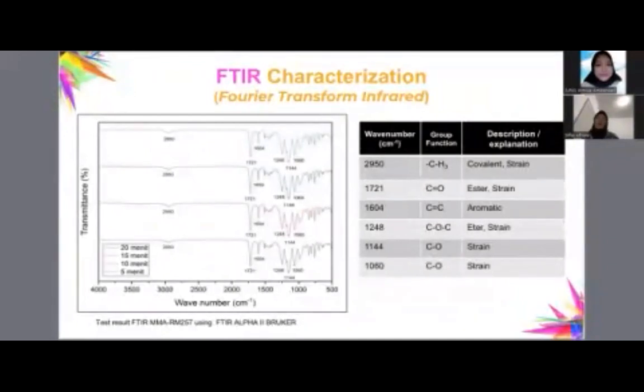FTIR. FTIR is used to determine the chemical functional groups in the sample. This is the result of the FTIR test on the MMA RM257 thin film. The absorption peaks are at 2,950, indicating a CH3 bond; 1,721, indicating a C=O double bond; 1,604, indicating an aromatic functional group; 1,248, indicating a C-O-C bond; and 1,144 and 1,060, indicating a C-O bond.